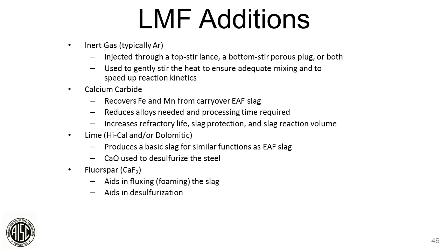Calcium carbide is something we add as well. Its job is to kill the slag and get the FeO out of the slag and MnO out of the slag and have it report back to the steel. It's also important for improving the basicity of the slag chemistry so it doesn't attack the brick. We add lime, high cal and dolomitic lime, again, to create the flux, the slag layer. And then we use fluorspar, calcium fluoride. It's basically a catalyst that fluxes the slag, makes it thin out quicker, and it aids in the desulfurization of the steel. Next slide, please.